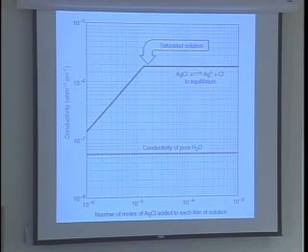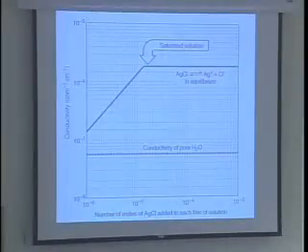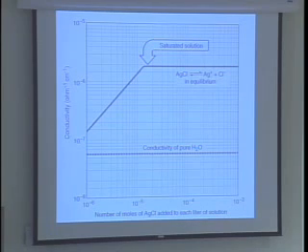So that would be a concentration of 10 to the minus 5 molar. And then what happens? We keep adding silver chloride, but the conductivity doesn't change. So what do you think is happening? If you could stare at the beaker, you'd see the silver chloride just falling to the bottom. So the knee in the curve indicates that we've reached saturation solubility. So that's good. So we have evidence to support.